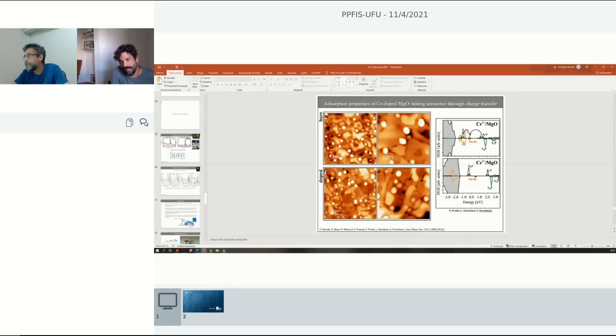And the way they're going to exchange or align the states, like the oxygen 2p states, to the oxide itself, actually makes electrons be promoted to one side and back and forth. But usually they are not prone to become like a quantum dot, because in a quantum dot you have such a dramatic change in the electronic structure of the particle that the properties are related to the particle itself. And then here is the conjugation of the particle on that oxide.